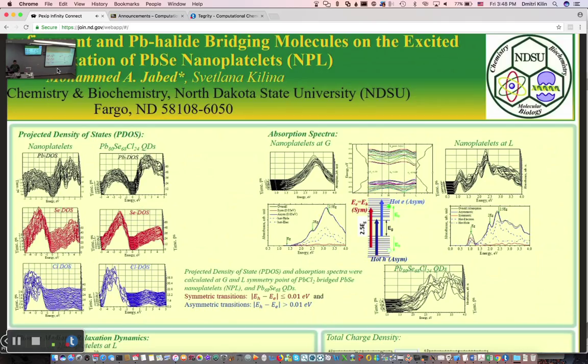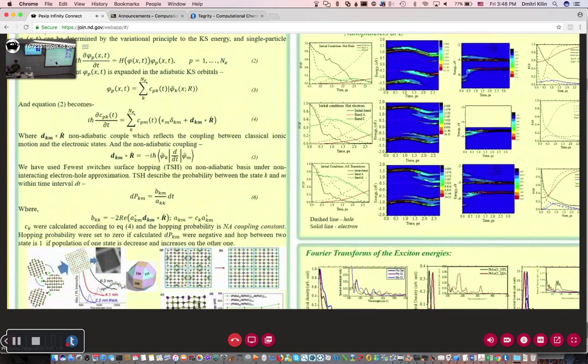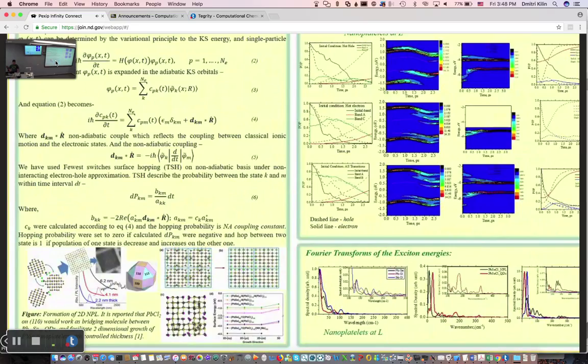Because your quantum dot doesn't have such a nice symmetry of the bulk structure anymore, due to the surface effects. And again, you can clearly see it at zero temperature, when you compare the nanoplates and this just optimized quantum dot. You already see that this definitely has much less symmetry compared to your nanoplate. Losing the symmetry means you really have disorder on the surface, which results in smearing these nice discrete peaks. But then why do we always say that increasing the confinement makes the bands ideal?